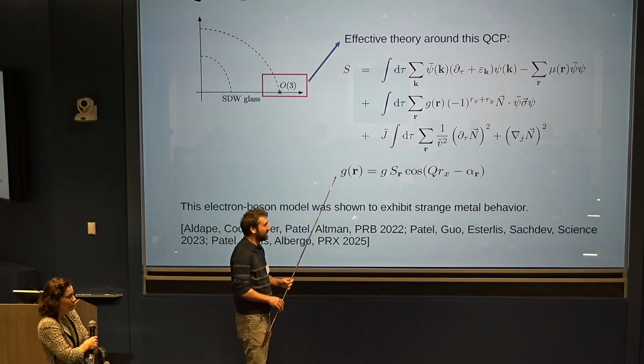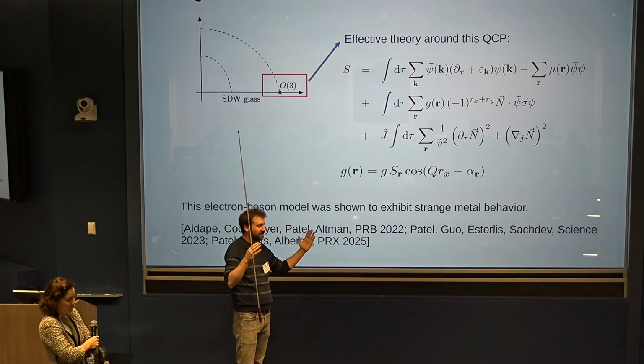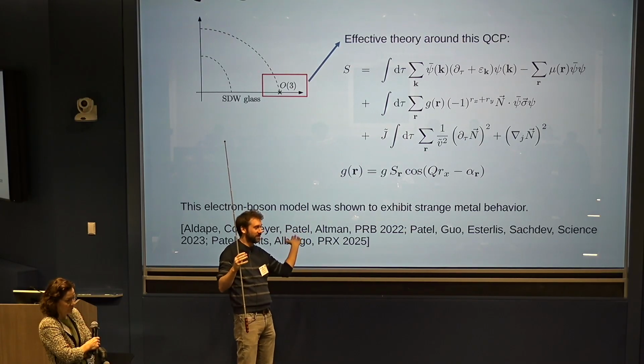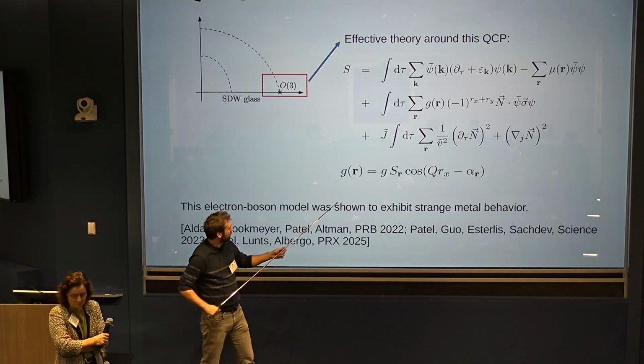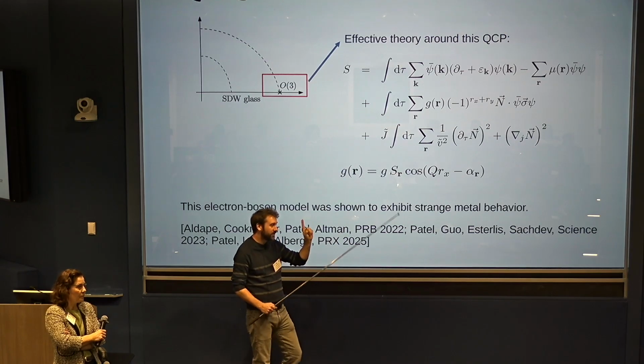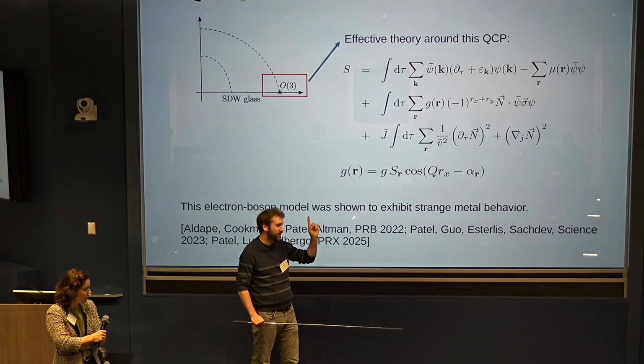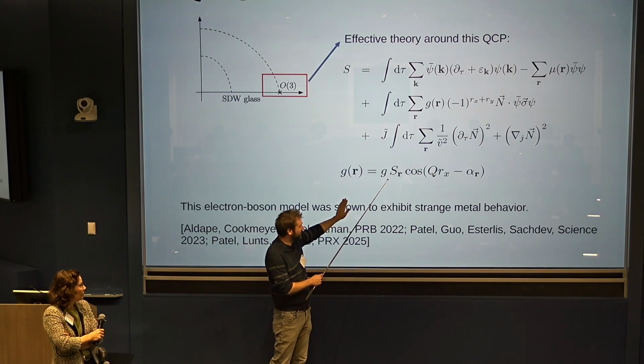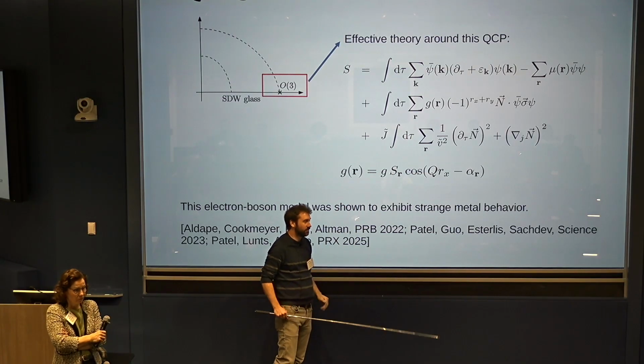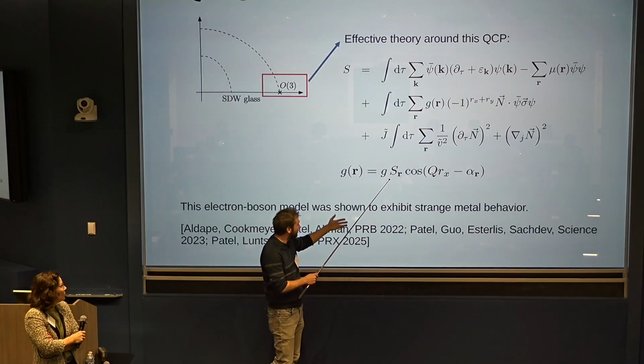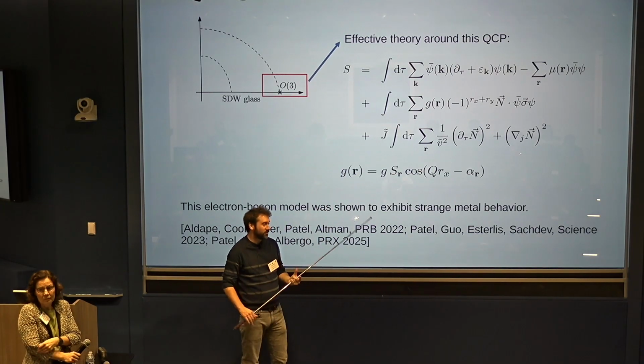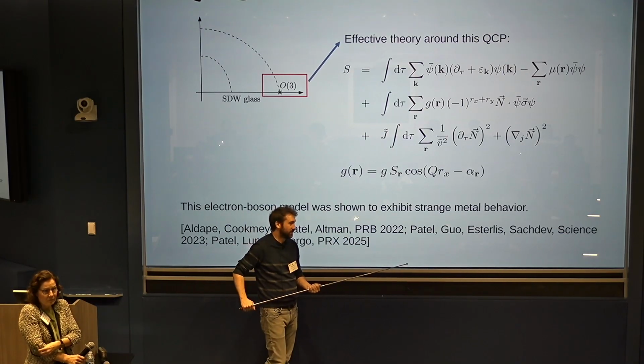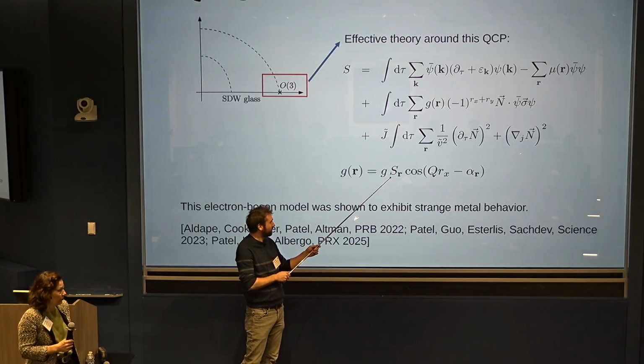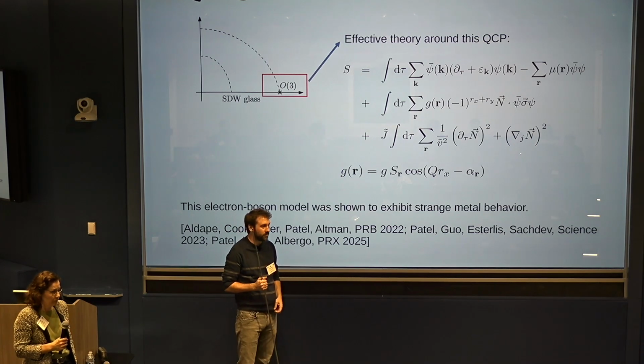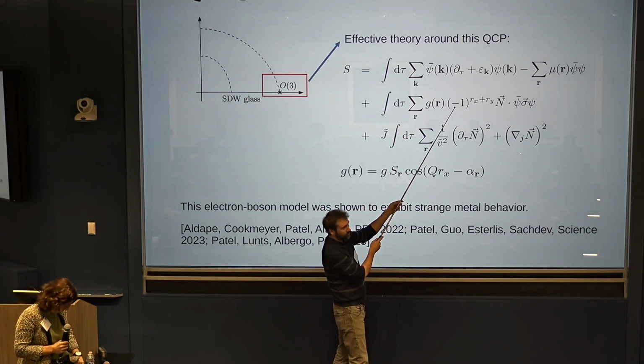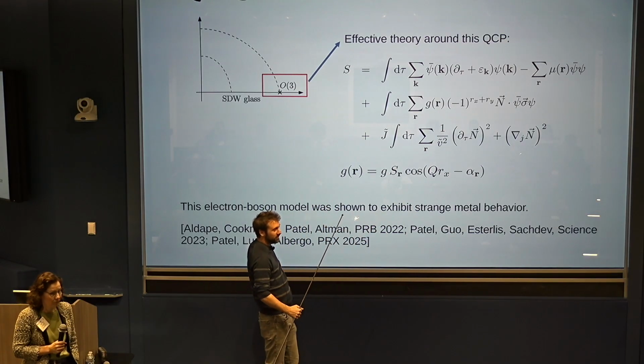Oh, it never actually, okay. It's a very bimodal distribution. It's actually never zero. It's just plus minus, like an Edwards-Anderson type of plus minus, plus minus. It has zero average. Why? Because this is the Ising spin degree of freedom, and in the glassy order it's going to be randomly up or down as a function of position. There's no long-range ferromagnetic order in this Ising degree of freedom. That's all you need, and it can be an Ising spin glass. Even if there are no dislocations, it will be an unfrustrated system, but still it will have random directions. I don't think you ever have long-range ferromagnetic order in this. Antiferromagnetic. You're talking about the antiferromagnetic component here. Sorry, yes, you're right. I always strip it off and turn the antiferromagnet into a ferromagnet. Yes.